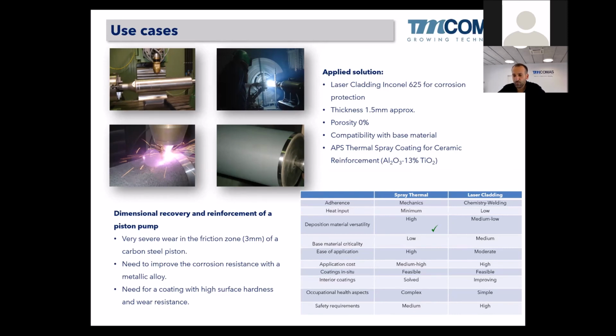So it's clear that in this case, the best option for a corrosion protection layer is laser cladding, because it has zero porosity, while in thermal spray we could have had some porosity. So the best solution for the corrosion resistant sublayer is laser, and the best option for the wear resistant top coat is thermal spray, because we have to spray a ceramic, and the only way to spray a ceramic is by thermal spray. So this is it.